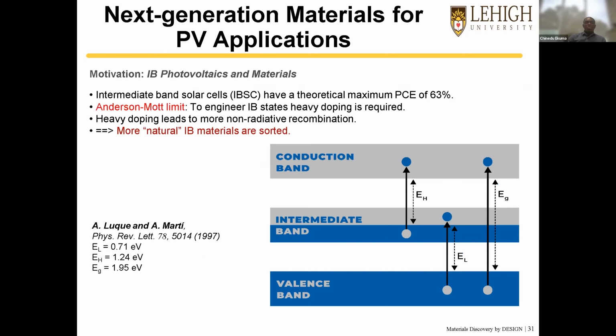Now, we also looked at other types of group 4 monochalcogenides, and our interest in this is that GeS and SnS, for example, are very good photovoltaic materials. But for us, when we started screening these materials, they showed very interesting properties that are in line with what Luque and Martí proposed in the language of intermediate band systems, which are theorized to have power conversion efficiency of up to 63%, which goes beyond the Shockley-Queisser limit of 32%.